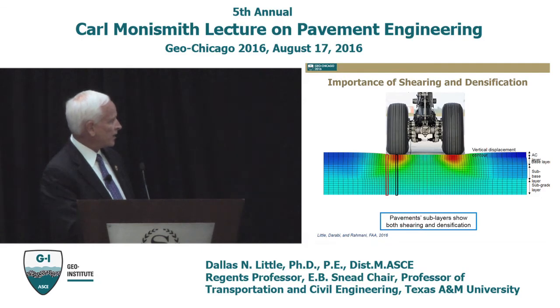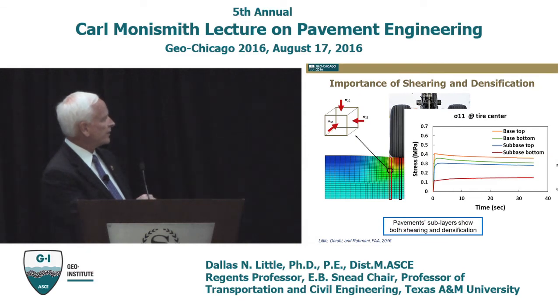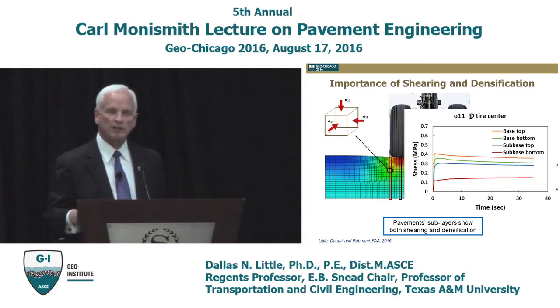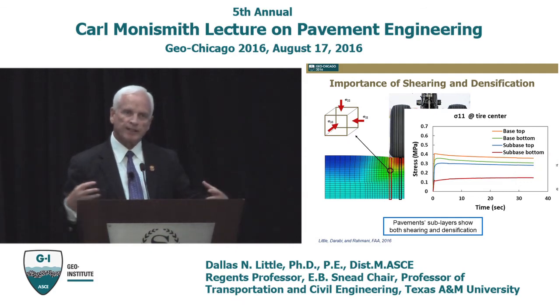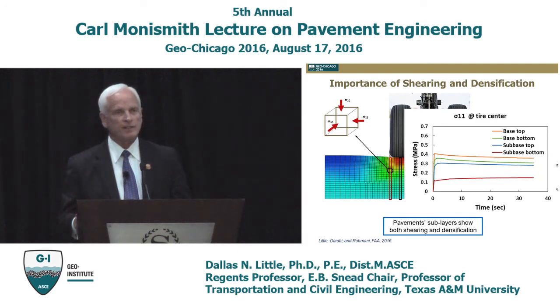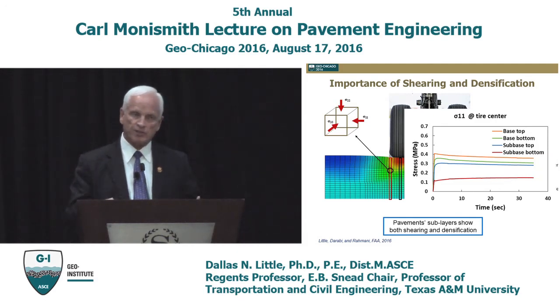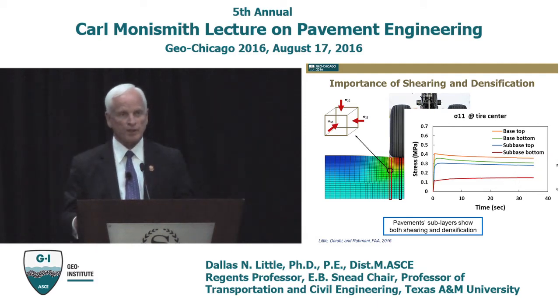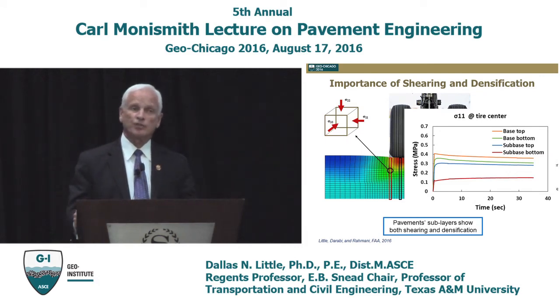So here's a model of one of the aircraft that we evaluated, and our finite element matrix there. As you look here and look at the sigma 1,1, which is the confining stresses, you can see that they are very much lower when you get down here to the subgrade, only something like 14, 15 psi, much lower than they are, of course, in the asphalt and the near surface layers, but that's sufficient in a CBR subgrade according to our model to cause consolidation, which causes densification-induced plastic strain. So this model evaluates plastic strain in the sublayers, the unbound layers, due to both densification as well as shear stresses. And it takes both to mimic what's going on out there in the field.